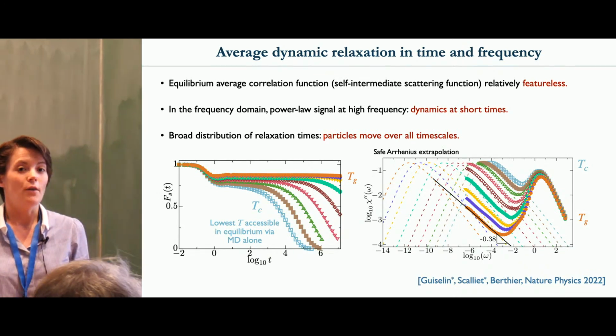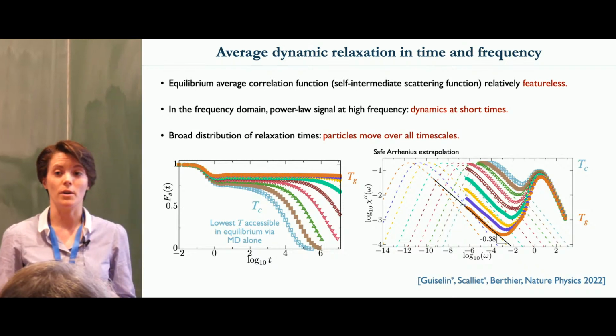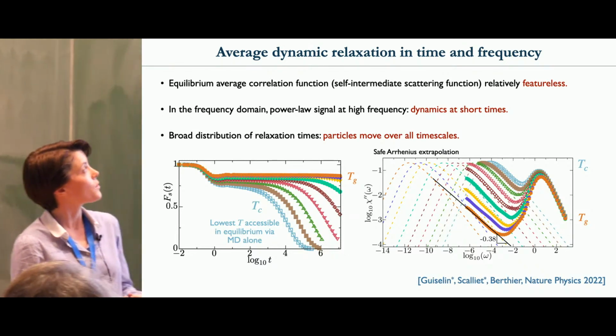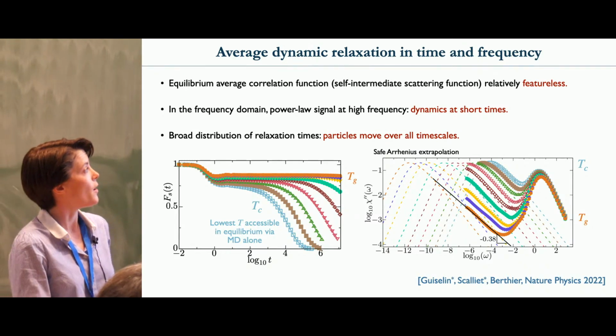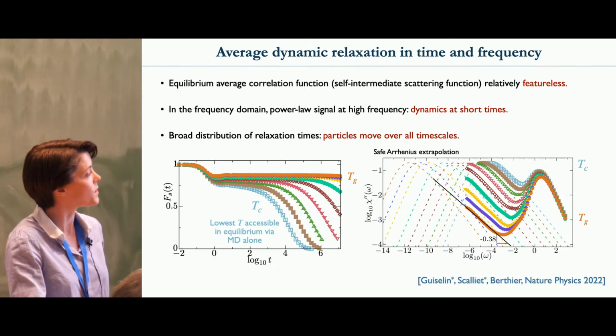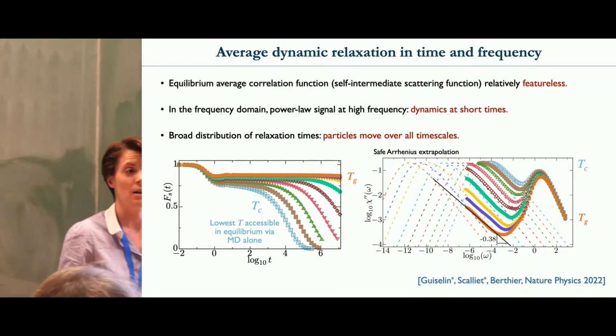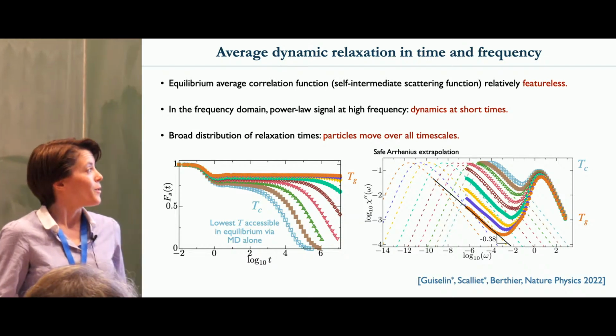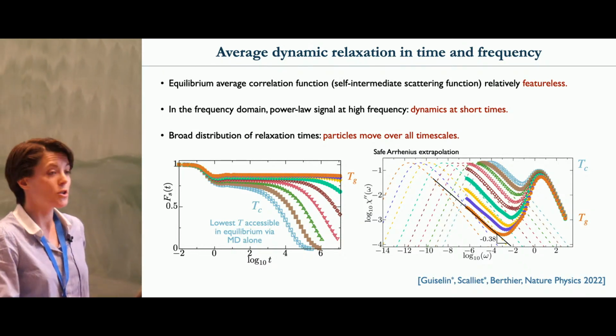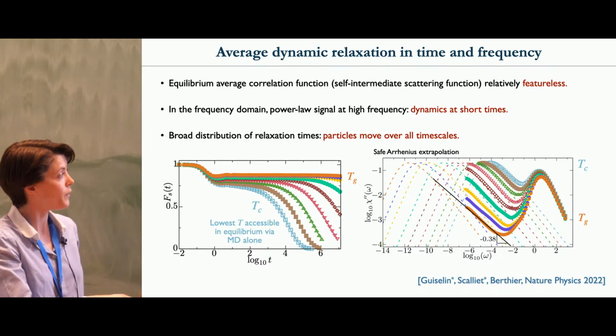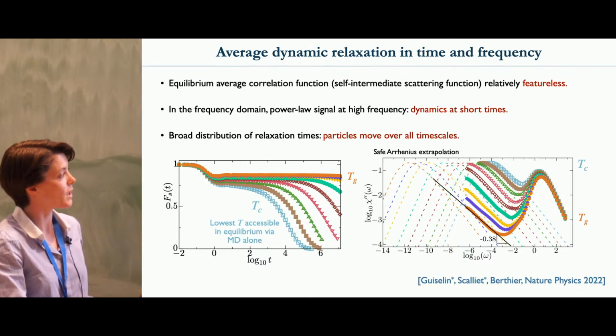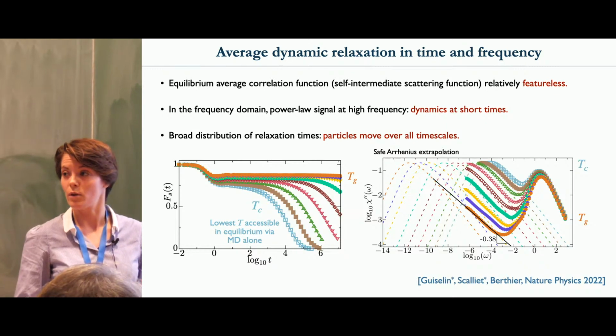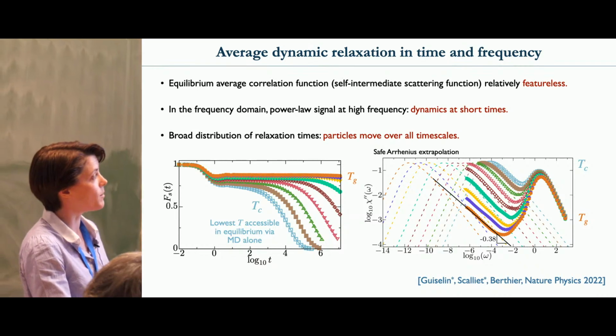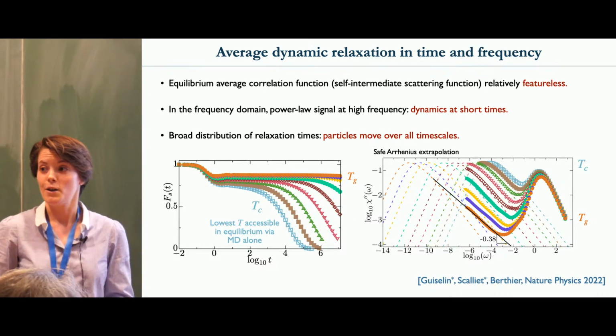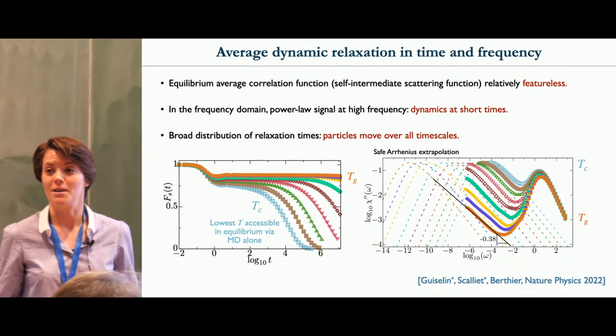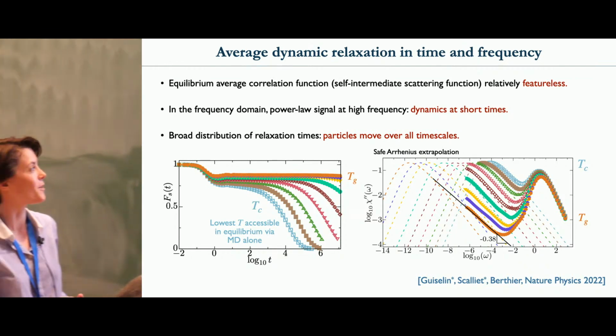So first I want to discuss the average correlation function. So these have been computed over and over in many different systems in the past decades. This corresponds, for example, to the self-intermediate scattering function. So this correlation function is shown here. It goes from 1 to 0 at long times. Here I'm showing the results in logarithmic scale. And this plot was actually shown this morning. The main point that I want to make here is that all these curves here are measured in the regime that was not available before. So here, this blue curve here corresponds to the mode coupling crossover or the computer glass transition. And this corresponds to the lowest temperature that was available before. And now, starting with these equilibrium samples, we can run the dynamics down to temperatures that correspond to the experimental glass transition. So if you look at this plot, you think, well, this is rather featureless because you mainly just measure a plateau. You wasted your simulation resources.